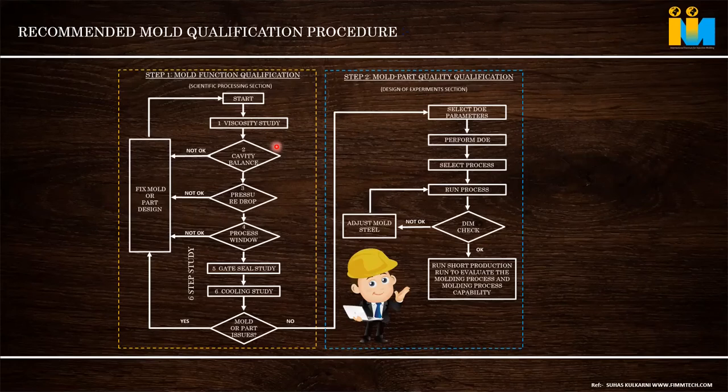Devin, can you give your idea? Check the physical part. Yes, absolutely right. When the part comes out, that's the easiest method. Check it with a quick temperature measuring equipment. So we'll know. If I'm running a polycarbonate part and when I check it is coming at 40 or 50 degrees, it's because I am giving over cooling time.